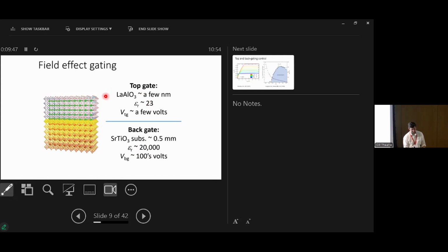Or we have lanthanum aluminate, which is a few nanometers thick, so orders of magnitude thinner. Dielectric constant is smaller, so it's less easy to move charge. But because it's so thin, the capacitance is very large. So we only need actually a few volts to move carriers into the interface or away from the interface and to tune the superconductivity.